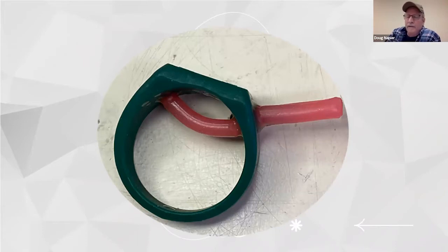Here's a piece that we were talking about earlier. When you get into porosity, this piece is fairly solid. If you look where the sprue is attached, that's the thickest part of that design. Most people would take this design and sprue it on the bottom of the shank because it's the easiest place to clip and grind, but they don't realize that when they cast this piece, the thickest area is going to solidify last. And if it doesn't have a place to feed, then you're going to get porosity in that.